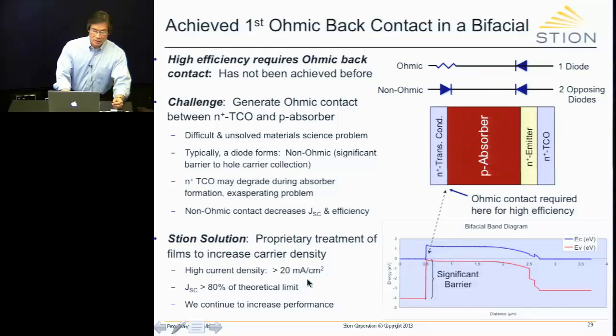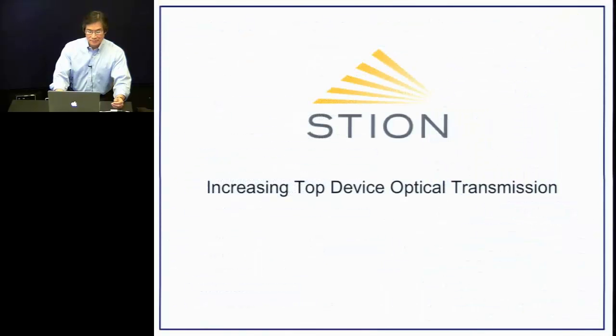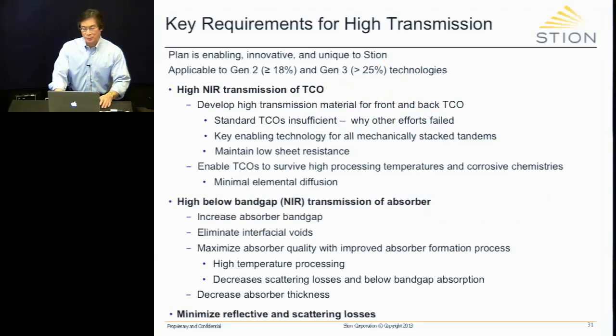And our current densities are greater than 20 milliamps per square centimeter, which is 80% of the theoretical limit. So it tells you that we've made a major impact in that region. But it's a very important problem, an ohmic contact for a bifacial top device. Okay, so we talked about the efficiency. Now let's talk about the transmission, which is really the more important issue here.